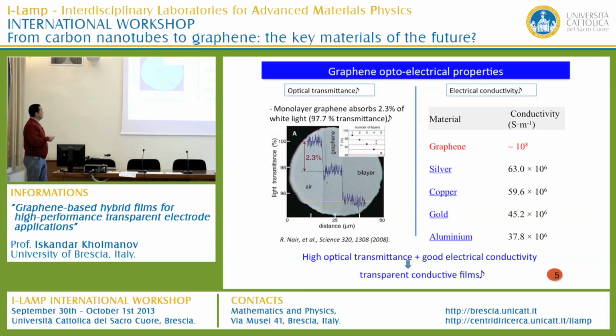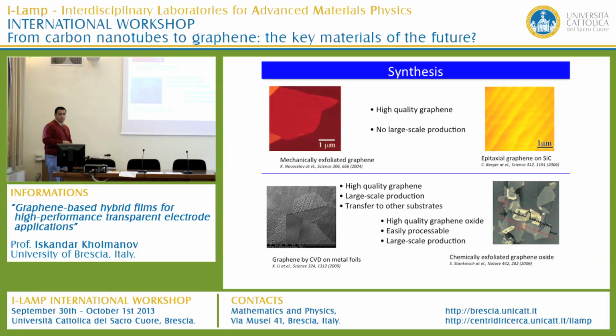You know this, it was also shown yesterday. The monolayer graphene absorbs about 2.3% of visible light, so a very high optical transmittance, higher than 97%, can be obtained. Another feature is that graphene has a very high electrical conductivity. The combination of the optical properties with the electrical conductivity demonstrates that graphene is a promising material for transparent conductive film applications.